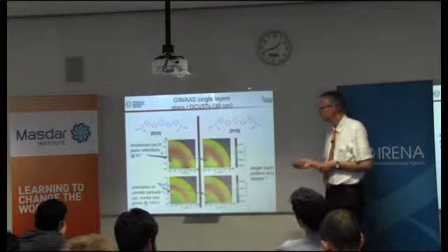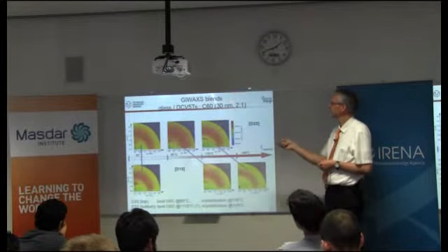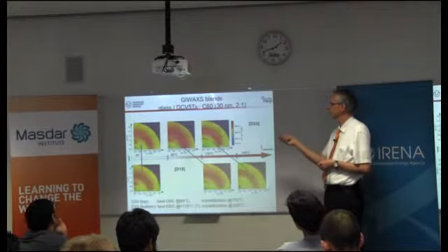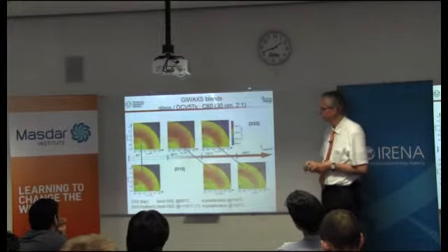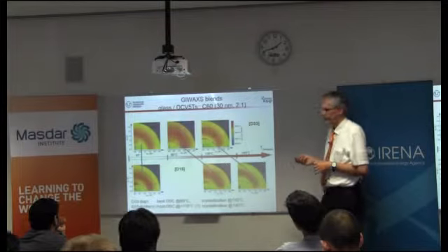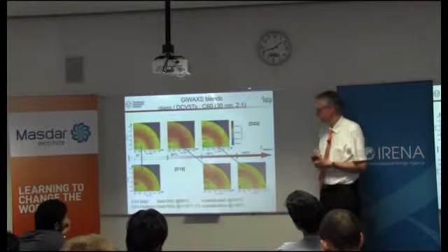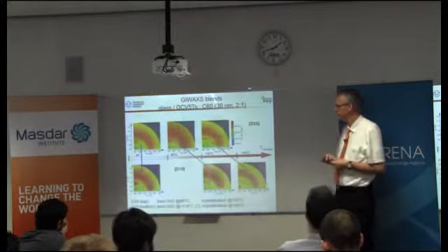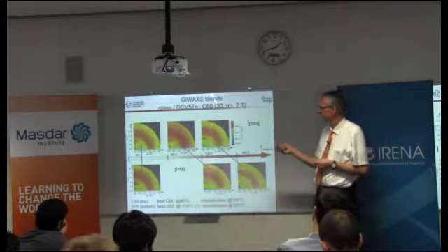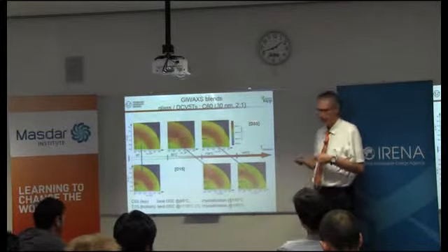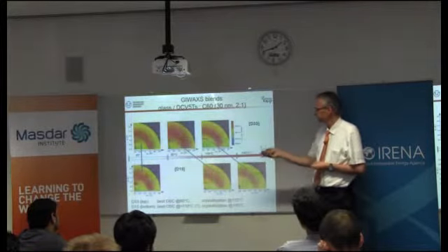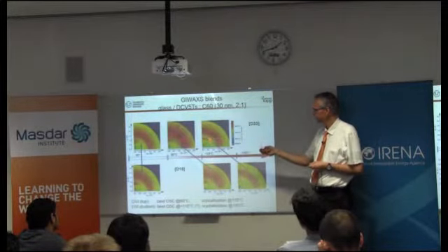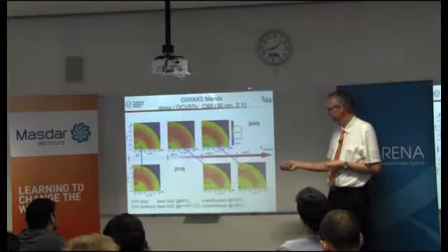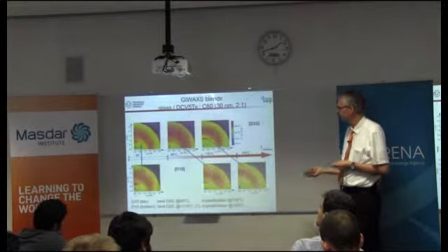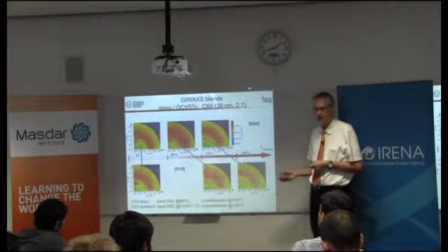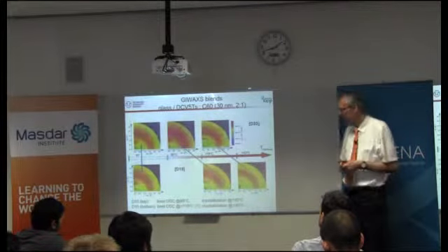But the main difference is when he looked at the blends again of the molecules with C60, with the fullerene, and the main message was that the molecules actually behave very similar, but on different temperature scales. What he found out is that the 3,3 molecule, which we thought is the better one, orders already at lower temperatures than the 1,5. If you go to 140 degrees, the 1,5 also orders very nicely.